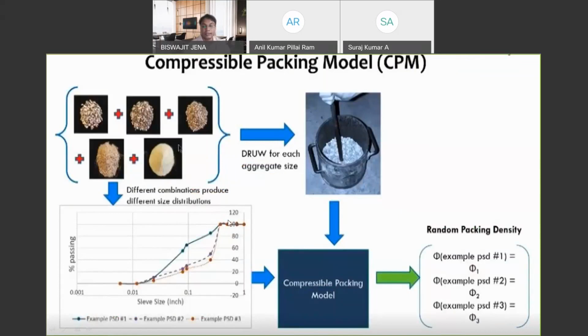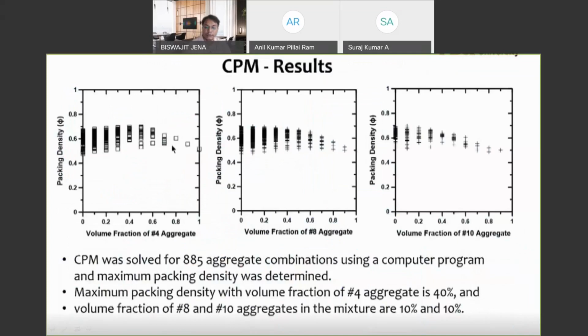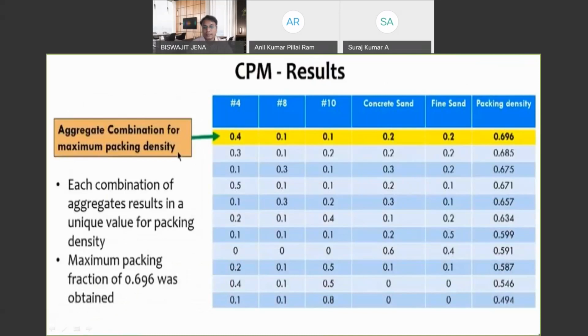By using a MATLAB program, these are some plots for more than 885 different aggregate combinations. We have a MATLAB code formulated so that the mixing can be done within 5 seconds. Then you plot the random packing density as a function of the volume fraction of different aggregates, and you can find where the maxima in the packing density is for different combinations. Based on those combinations from the MATLAB code, we picked the one with the maximum packing density. In this case it is 0.696, where I have 40% of number 4 size aggregates, 10% of number 8 aggregates, 10% of number 10 size aggregates, 20% of concrete sand, which is 0.6 mm, and 20% of fine sand, which is 0.2 mm.